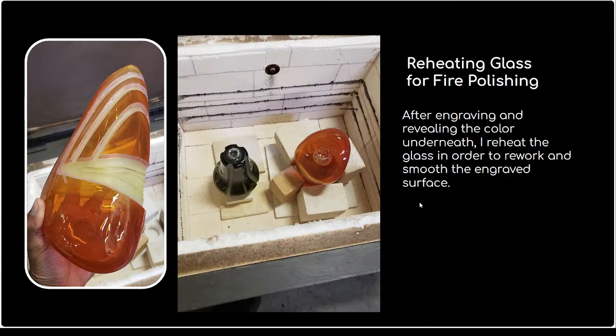And what we're not doing is giving it back its integrity. It's not one surface again. So by fire polishing, we can give back integrity to that surface, meaning that the outside surface becomes strong again. And even though glass breaks under tension, not compression, I still argue that it makes the glass more brittle if the surface has some sort of scratch or sandblasting or engraving texture to it. So even though it's not going to break on the inside, there is a fragility to the overall structure.